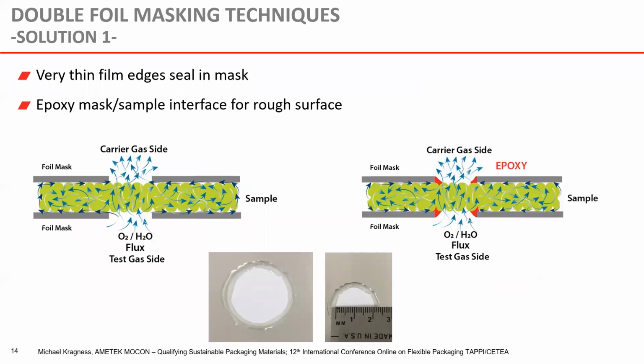So talking a little bit more about double foil masking, we have these diagrams here. If you take a cross section of a double foil mask, what's going on? So in this example, we have oxygen, or H2O, on one side. So that's moving into the material. And then because it's paper, it's going to want to move all throughout the material because it has porosity. So diffusion being random, it's going to want to move through the material and through the sides and basically anywhere it can go.